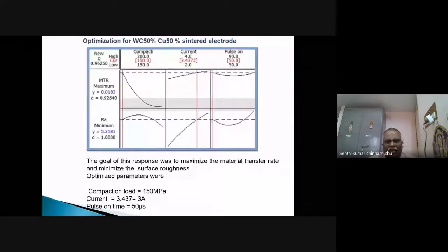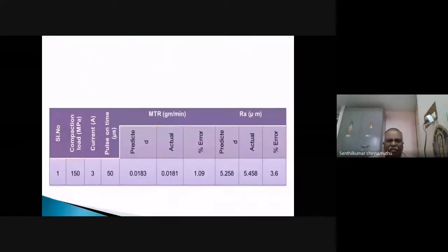Again, we have to go for the validity test: 150 megapascal, current of 3 amps and pulse on time of 50 microseconds. The actual values we get with the optimized parameters are a metal transfer rate of 0.0181 and surface roughness of 5.458. The percentage error for metal transfer rate is 1.09 and for surface roughness is 3.6, which is below plus or minus 10%. It is a good agreement between the predicted and actual value, and it confirms the reproducibility of the experiment.